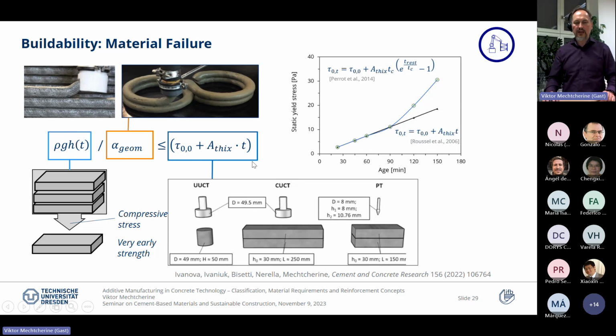I hope you can see my cursor. And on the other hand, we have the initial yield stress, and then we have some development in time, which depends on the thixotropy of material. Good. We can use a formula suggested by Nicolas Roussel or by Perrot, depending on which time interval is interesting here. So at the beginning, it's pretty linear, this development in time. And to derive these properties, we need some robust approach. You can try to use rotational rheometer method, but not in the usual regime, but really start very, very slowly to capture the quasi-static properties of the material. Or you can go for this kind of penetration test or uniaxial compression test. Again, it's on fresh material, so it's a compression test, but performed on fresh material.